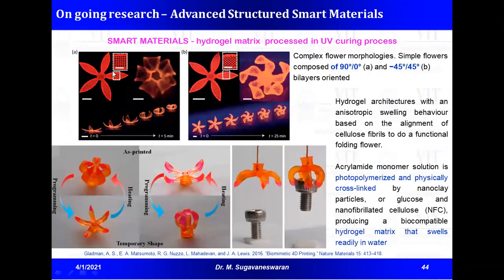And one more possible application of the stacking sequence could be soft robotics. Here you can see the application of laminate orientation. For example, in this case, the part is made through a smart material, and apart from the material behavior, the structure is also playing a major role. So as reported, the component is made of square cellular cavity, that is layup is like crisscross or cross ply. Here it is inclined diagonal cavity. Just by changing the layup direction, we could control the distortion behavior of a material, and this distortion could be used according to our application.